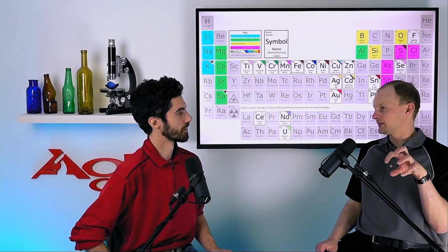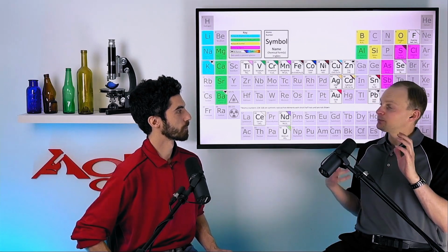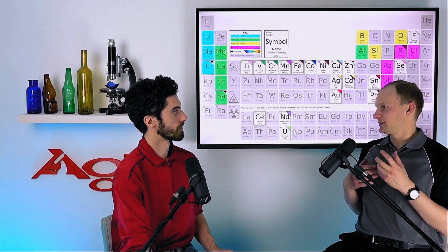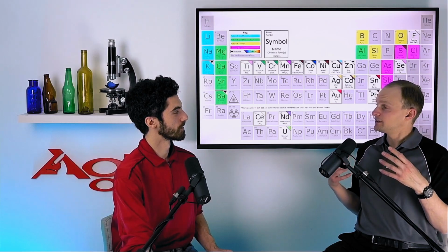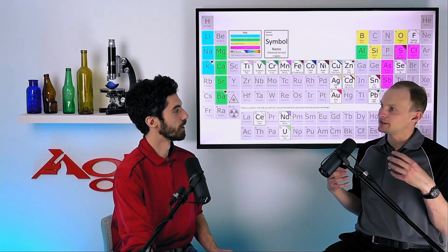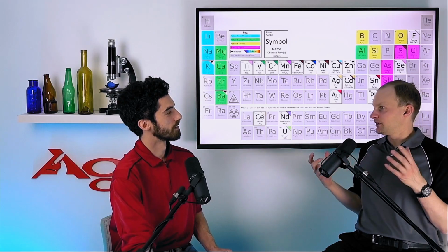I'm not gonna die of radiation poisoning. The uranium is in the oxide form, and again, it's in the glass structure. It's not coming out. But it provides this yellow-green color, which is very vibrant because it actually fluoresces under ultraviolet light. So, no kidding, in sunlight you have a little bit of ultraviolet light present.